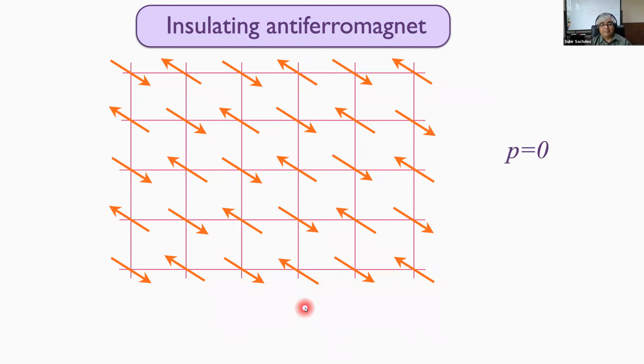Okay, so that's an experimental, very short introduction to a very confusing set of experiments. But what is the theoretical model we'd like to solve? Well, the theoretical model itself is also extremely simple, and I'll write it down now. So you have a square lattice and it is in the parent compound at P equals 0, you have 1 electron per site. So this is a certain concentration of oxygen or dopants in the material. And these electrons are frozen in their charge, but their spins have this antiferromagnetic arrangement. So this is an insulator, and the spins have this staggered structure.